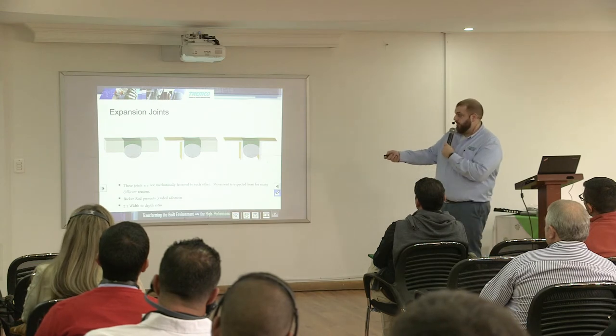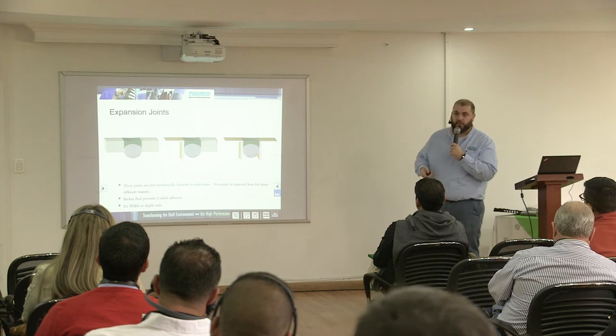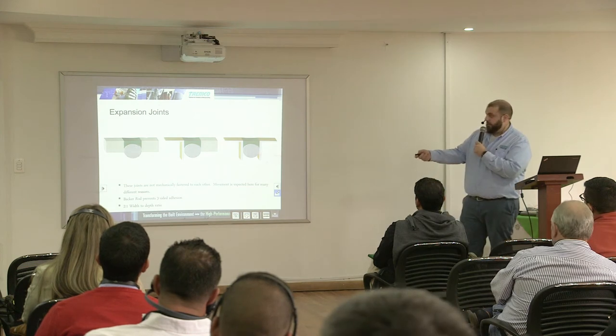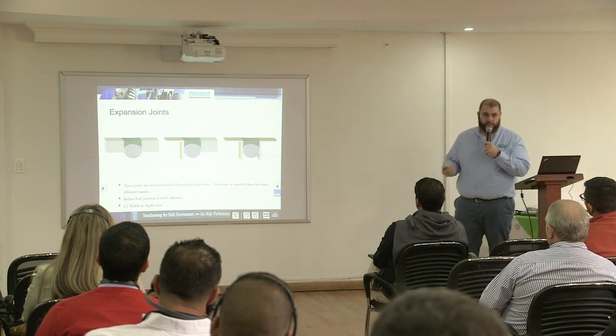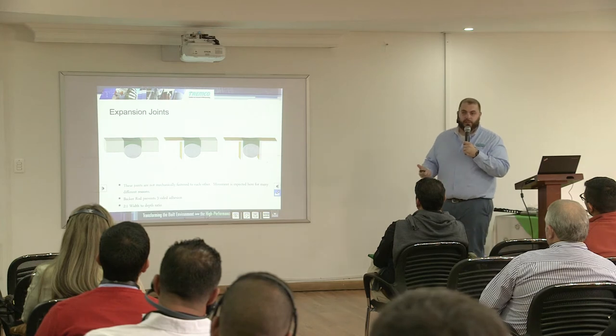So if we have a 1-inch joint, we have 1/2 inch depth of material. If we have a 1/2 inch joint, we have 1/4 inch depth of material. That's a widely accepted rule of thumb in the sealant world. Once you start getting over that 1/2 inch depth, the problem is you have so much sealant in that joint, the joint cannot flex and move, and you'll end up seeing tearing in it.